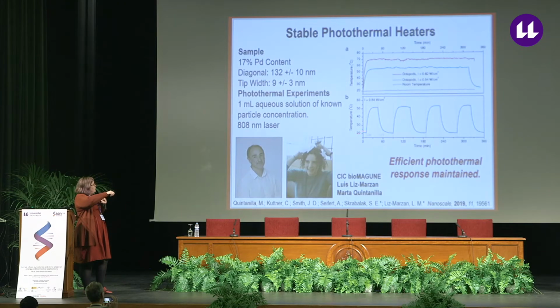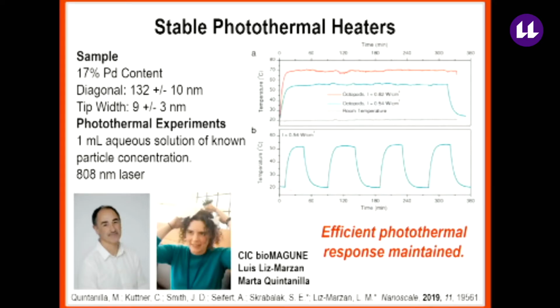And you can see that as you turn on the laser, the water heats up. As you turn it off, it cools back down, goes back up when you turn it on, and it's very recyclable, and also we can have quite stable photothermal responses over a very long time. And this is in contrast with many of the gold systems where for similar power inputs you will see substantial reshaping of the nanocrystals and a shift in their LSPR.